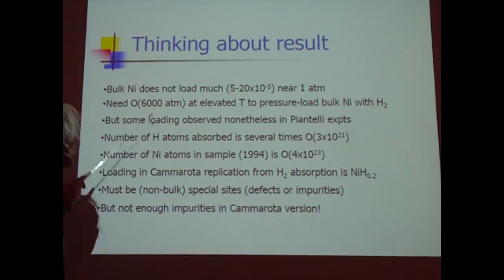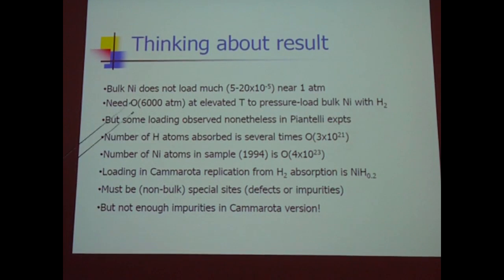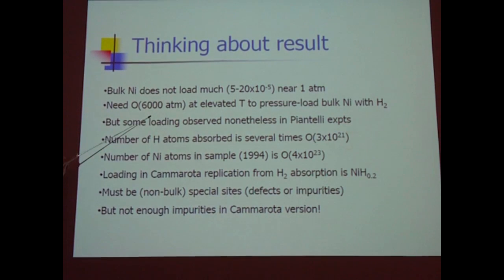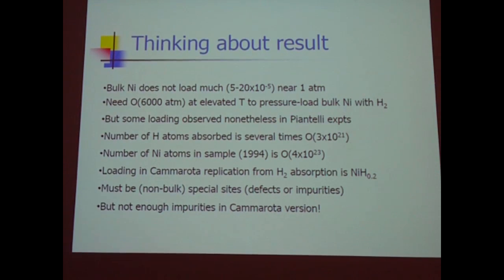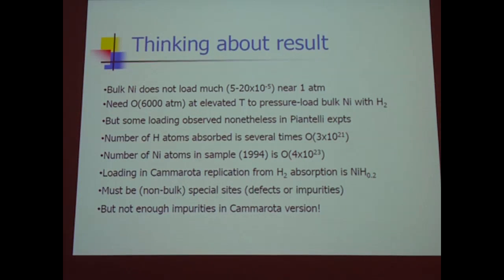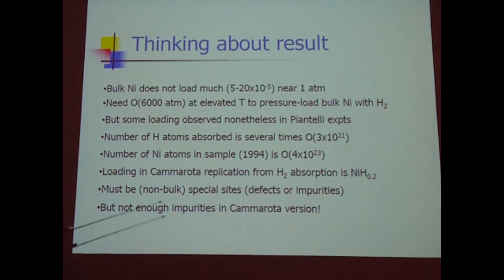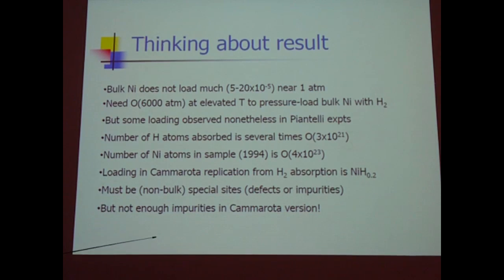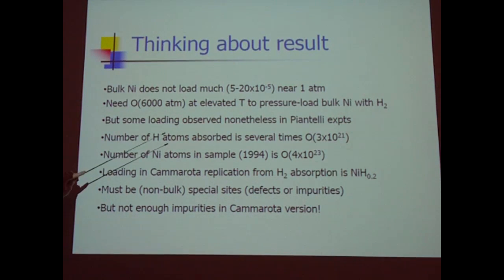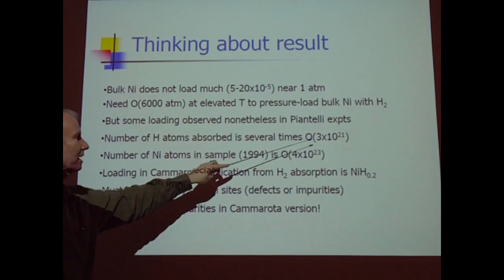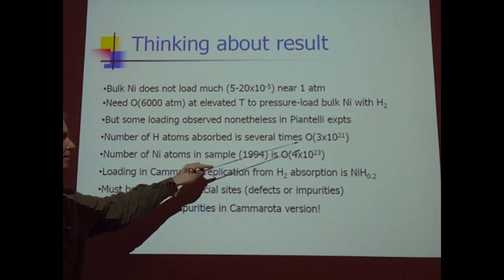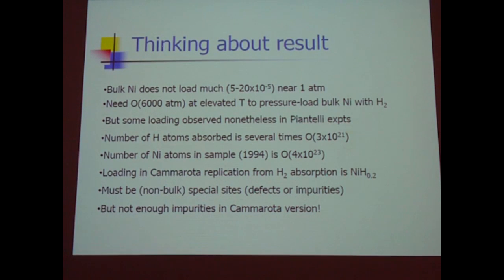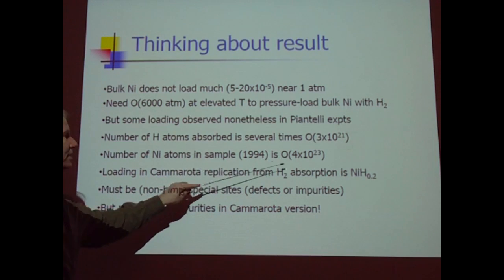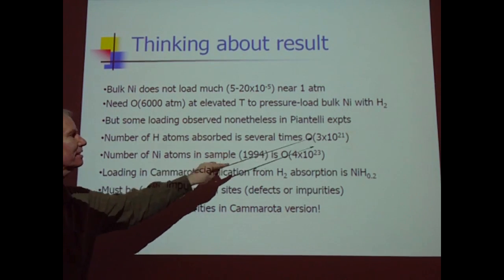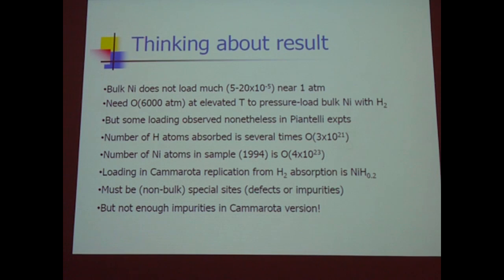Let's think about this. Bulk nickel doesn't load much. You need a lot more pressure to pressure load bulk nickel, and they're certainly not doing that. But they get some loading anyway. So the number of atoms they're getting absorbed, one of the numbers deduced from their data, is this number. The amount of nickel atoms in the sample is this number, and you look at this and look at this, and it's sort of close to 1%, which is way the heck more than bulk nickel can load.